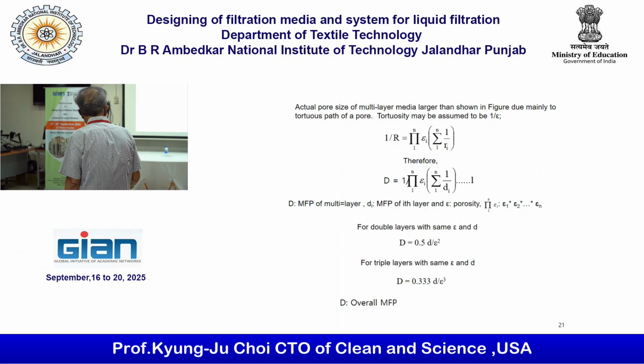Then the overall mean flow pore is 0.5 times the individual layer's mean flow pore divided by the square of porosity. What about the triple layer? The triple layer is something like that. Actually, this works.